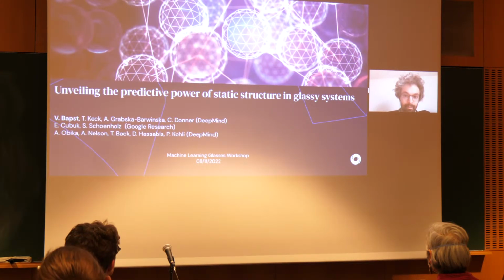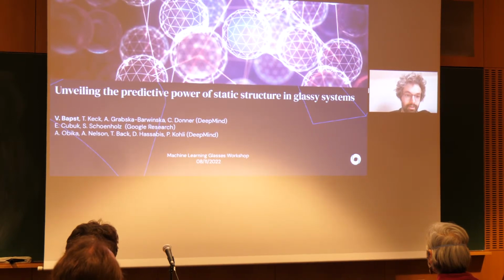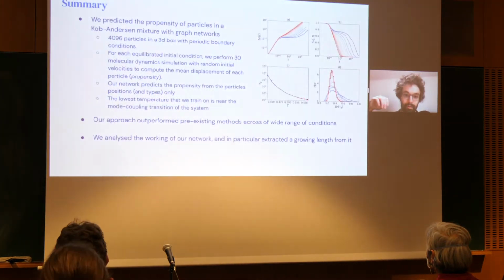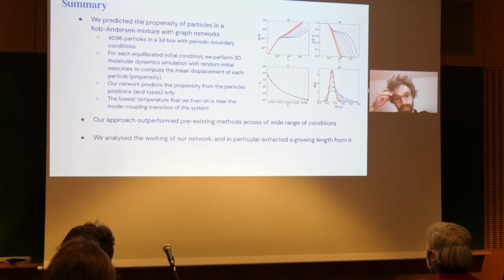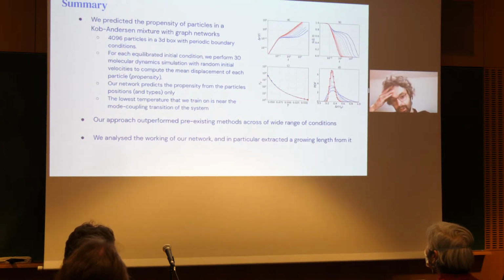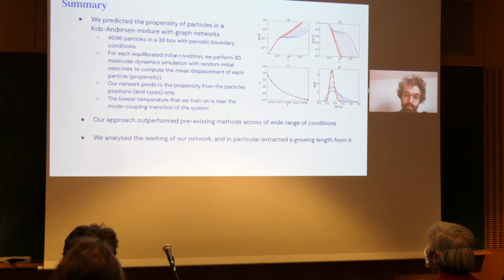On predicting the dynamics of glassy systems with graph neural networks. So this is a quick summary of the work. What we did in this work is predict the propensity of particles in a Kob-Andersen mixture with graph networks. We had about 4,000 particles in 3D, and we predicted the system at different temperatures, and for each equilibrated configuration, we additionally ran 30 dynamic simulations from there to compute the mean displacement, the propensity, and we predicted that with the network.